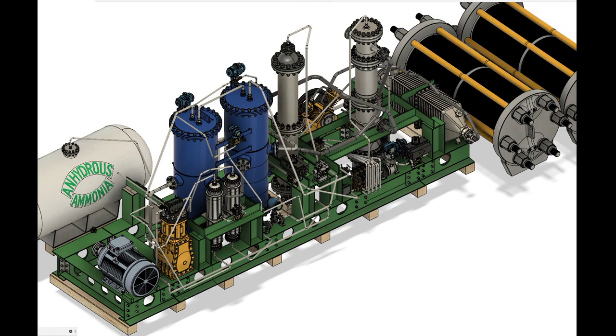Many modern ammonia converters make use of active cooling, or what's termed a cold wall converter, where cold ammonia is flushed alongside the wall of the converter to maintain a temperature lower than the synthesis gas inside the catalyst basket. This serves to attenuate nitriding and high-temperature hydrogen attack, preserving the life of the reactor. For the miniature plant, the designer must choose between a cooled and non-cooled design. This ultimately boils down to the budget and specific requirements on plant longevity.